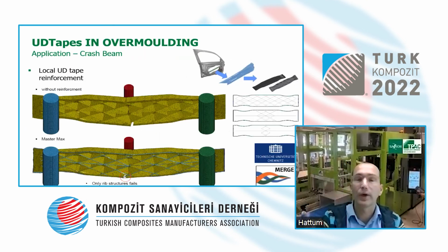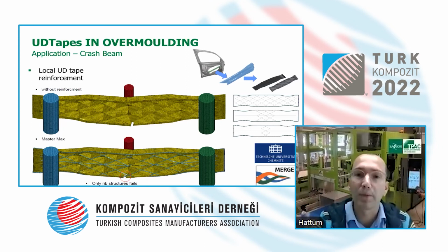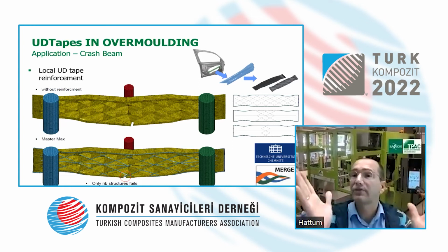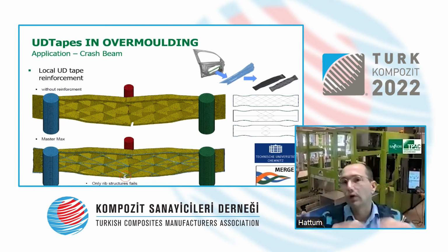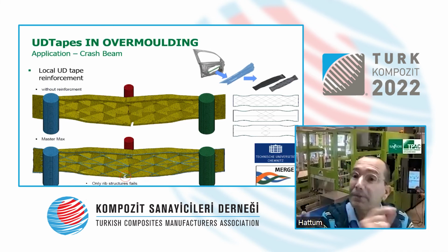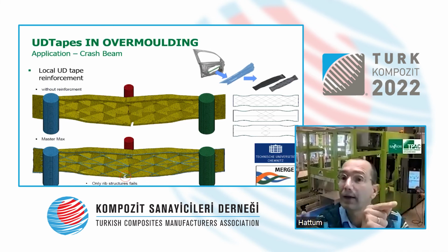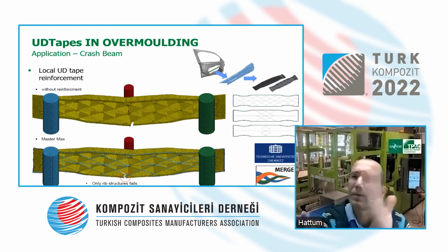So typically what we're doing, back to something that is most likely more your kind of background, an automotive application. This was a demonstrator we worked on together with the Technical University of Chemnitz in a European cluster of excellence. It's a crash barrier beam. My personal favorite material is glass fiber polypropylene because it's very cheap, it's widely used, you heat it up, you cool it down, and it's always brilliant, but especially the crash performance is good. So what we did in this specific project, we took out a crash beam of, I believe it's a Volkswagen door, but it doesn't matter.